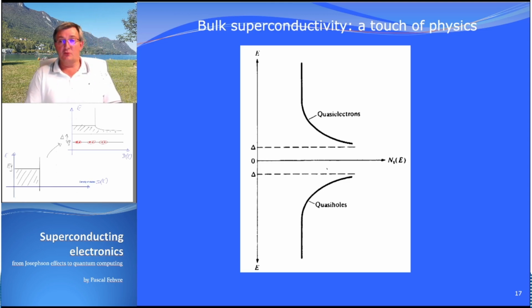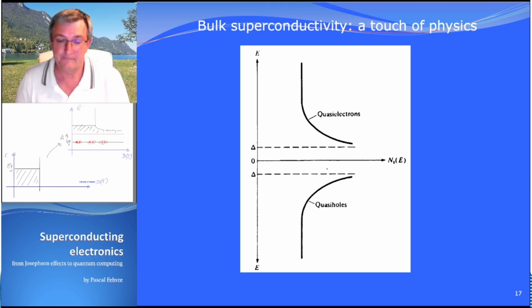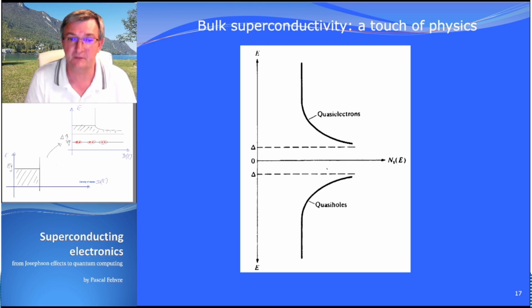And then when you cool down the system, it becomes, I would say, superconductor progressively. The order increases. At 0 K, you have a perfect order. All electrons are in Cooper pairs. They are bosons, and so they are in the same state. So there is perfect order. You have a macroscopic wave function associated to these Cooper pairs, and of course they have a perfect order, and the order parameter in phase transition is 1.